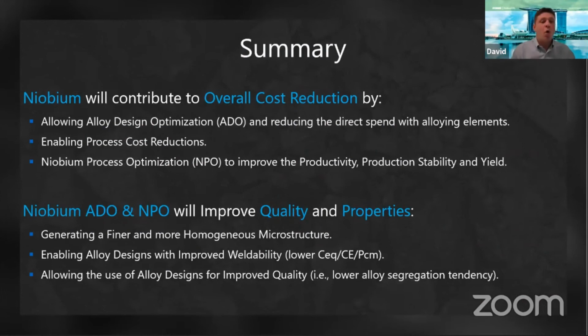So in summary, the niobium can contribute to reducing the overall cost by allowing alloy design optimization for reduced direct spend with alloying elements, and also enabling process cost reduction with the niobium process optimization, improving the productivity, the production stability, and the yield. On the quality side, niobium can generate a finer microstructure and enable alloy design with improved weldability, and allow also the use of alloy design for improved quality with more homogeneous and finer microstructures. And this is how we as CBMM believe that we can also contribute for the overall cost reduction by using niobium and using its properties to reduce the overall cost of producing steel.